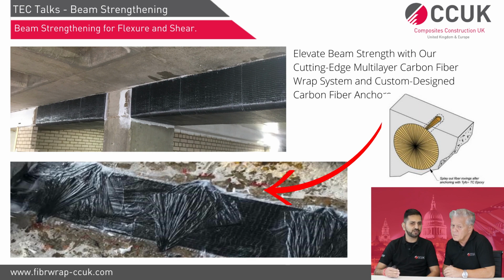They were adding additional stories on top of this 6-story structure, and the new steel columns were going right on top of the existing beams, which was generating point loads, and they had to strengthen the beams for additional moments and shear forces. So FRP was chosen there. The main reason was headroom, because if you go with the steel solution, you will reduce the headroom, which is not advisable, especially in a situation where you already have low headroom. So FRP was preferred there.